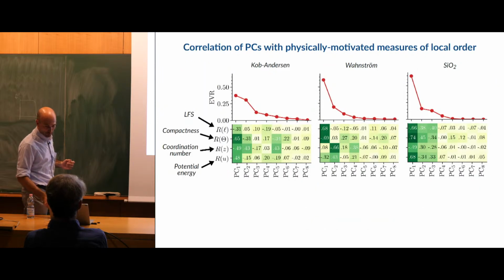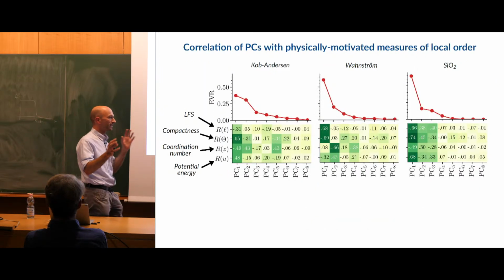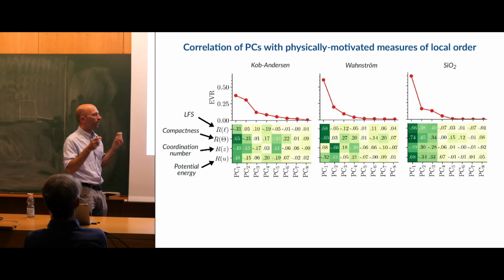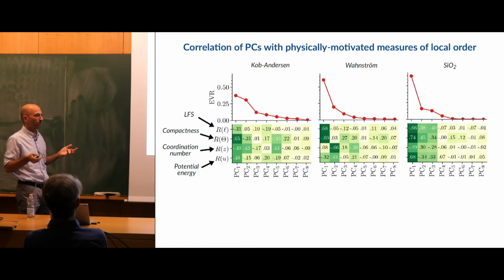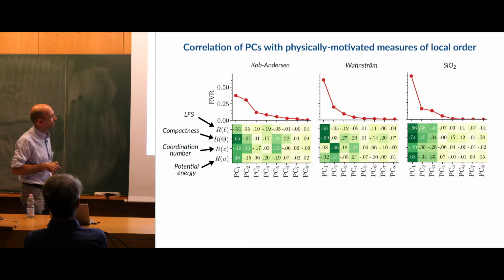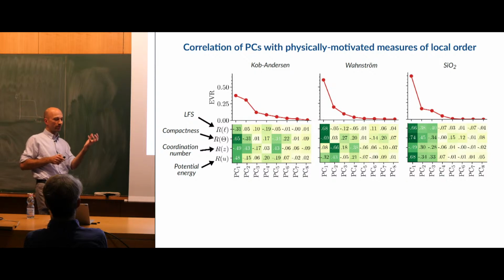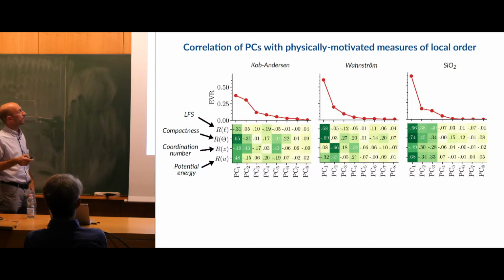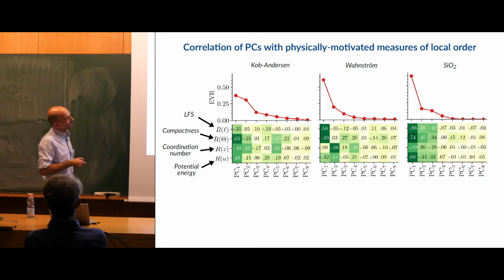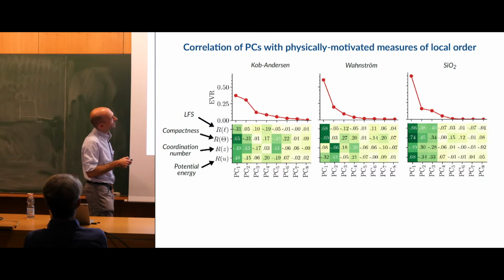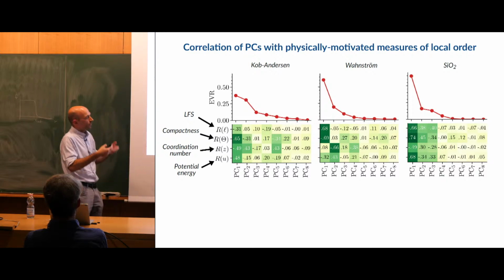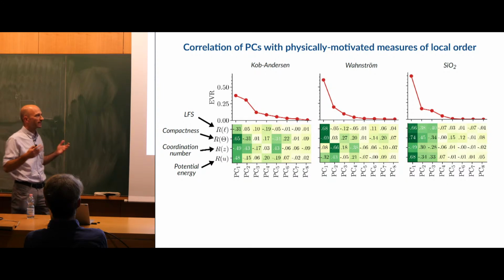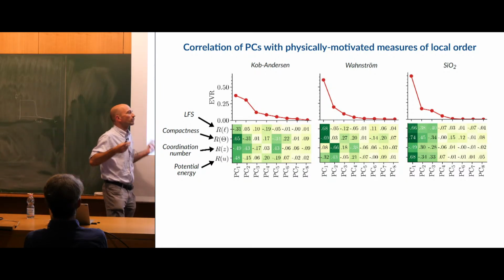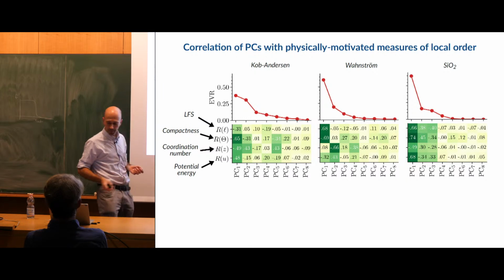And then it's also interesting to try to connect these reduced structural variables to physically motivated measures of local order. So for each principal component, we compute the correlation coefficient with potential energy, coordination number, a measure of how compact the local structure is, the theta parameter that we heard before, and also the LFS. And what we can see is that the first few principal components tend to be correlated with these physically motivated measures. So in a sense, they found these interesting fluctuations in the local structures automatically, by themselves.